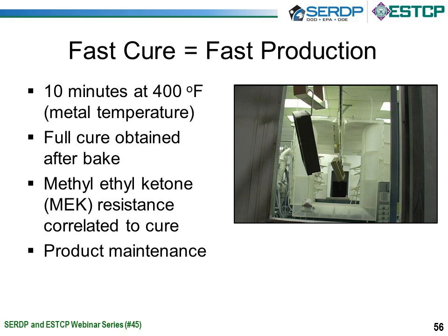That way, when the paint is taken out, you can be assured that the full cure of the technology is not a semi-cure that then becomes fully cured once it's applied to the asset, or that must sit around and continue the reaction for days. After 10 minutes, the product is fully cured.